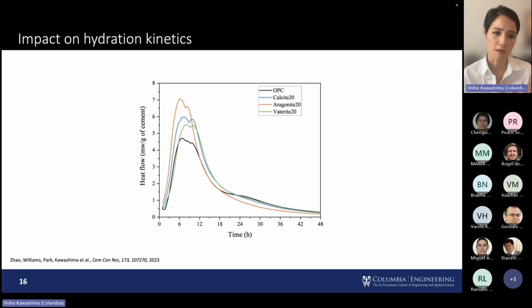So this isn't the main focus of the talk, but I just wanted to give you an idea of how these impact very basic properties. So we like to study hydration kinetics. And so these are all cement paste with 20% replacement of calcite, aragonite, and vaterite, those three different polymorphs. And we see that they all impact cement hydration kinetics differently, right? Note that this is all normalized with respect to mass of cement, so we're really focusing on the impact of these materials on cement hydration. And as expected, they all have a filler effect, so they all promote nucleation and growth. And so you see the shift and this increase in the peak of these hydration curves. And aragonite has the highest peak.